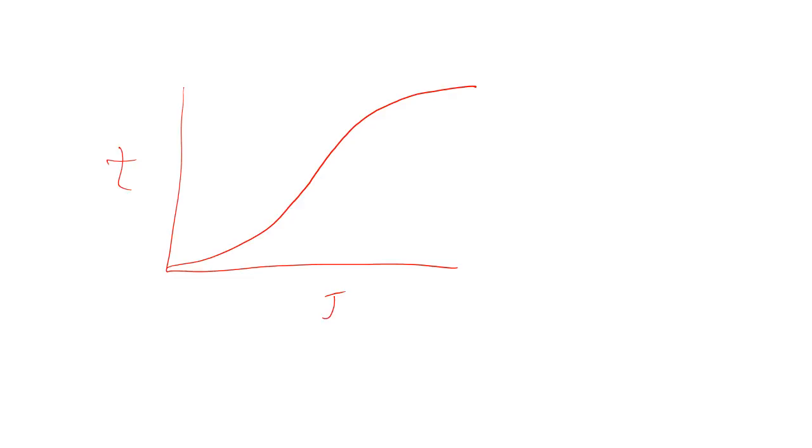Compliance curve. A couple of people plotted the relaxation curve rather than compliance. So this is T, this is J. We've got glassy, viscoelastic, rubbery, and viscous flow. And if we increase the temperature, this curve will shift that way. Higher temperature means that viscous flow happens more easily.